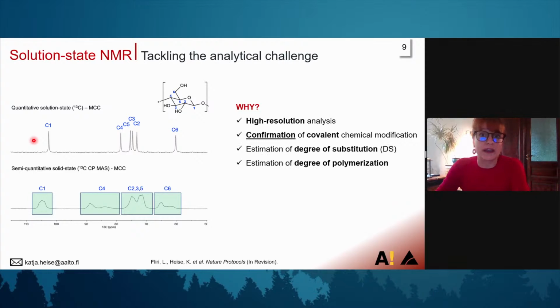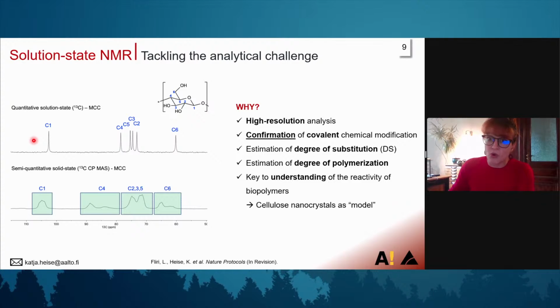You can also calculate a degree of substitution after modification, and you can also obtain from solution state NMR the degree of polymerization. And moreover, if we use cellulose nanocrystals for studying reaction chemistry, we can also use them as a model compound for studying the reactivity of cellulosics.